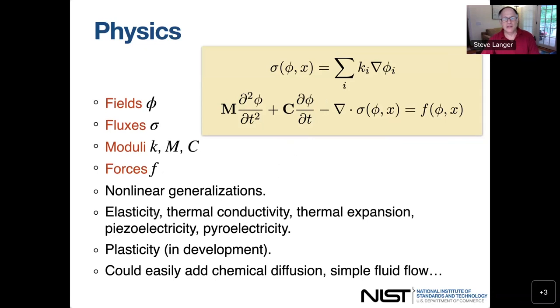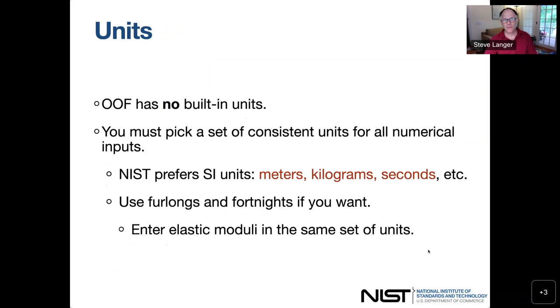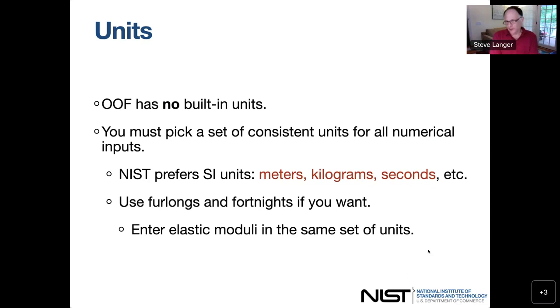This includes elasticity, thermal conductivity, thermal expansion, and piezo and pyroelectricity — all built into OOF. Plasticity is in development. Things that are easy to add because they're all of this form include chemical diffusion or simple fluid flow models. There are no built-in units in OOF; you can use whatever units you want as long as all your numerical inputs are in a consistent set of units. SI units are preferred, but it's not built into OOF.